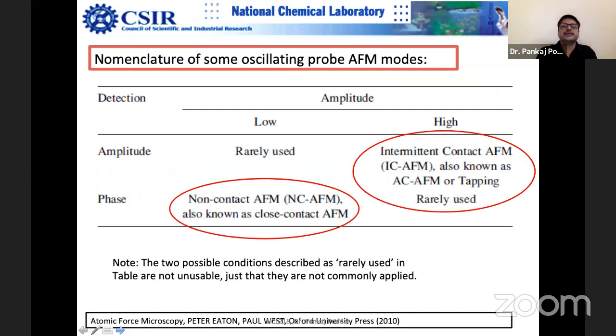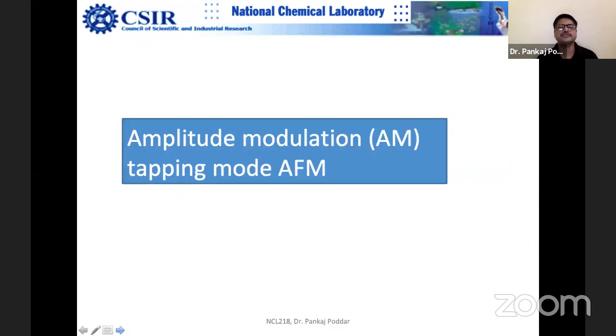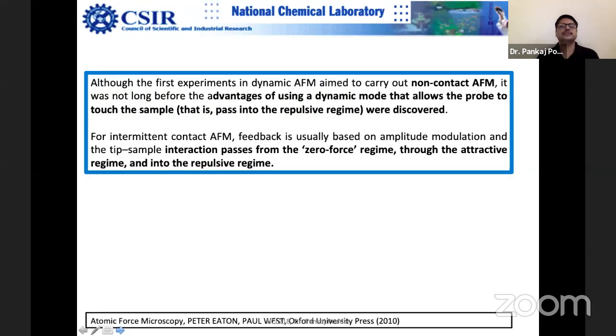So this is the summary of both the modes. When amplitude is high, that is called tapping mode, intermittent contact mode. There you mostly detect amplitude, and phase is also detected; in my laboratory, we detect phase also. When we are keeping the amplitude low, amplitude detection is not normally done. We use phase detection or frequency detection, which is not there in this table, but these days you can do that. Okay, so let us see next.